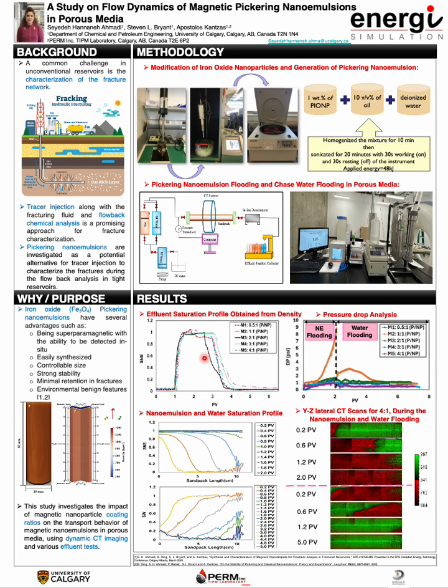And in the next graph, you can see the pressure drop for all experiments during both nanoemulsion flooding and water flooding. For all experiments, pressure drop builds up as the nanoemulsion invades the water-saturated sandpack up to 2 pore volumes of nanoemulsion injection. This phenomenon is attributed to the nanoemulsion's higher viscosity than water, which mitigates the tendency for viscous fingering.